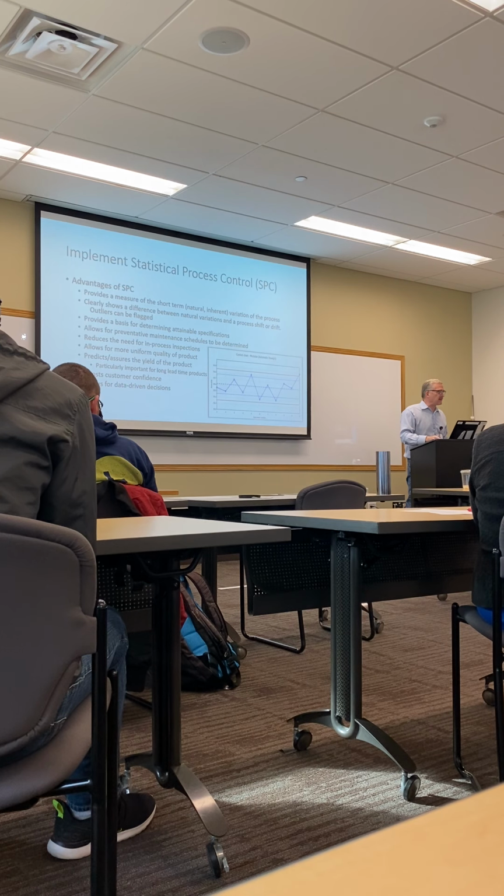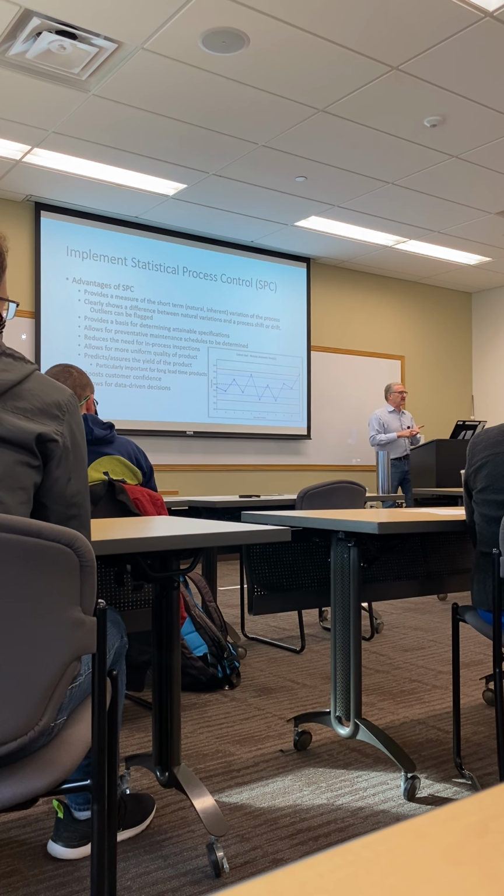That's all we know is at that step. At the next step, if we etch a hole in that oxide and the hole goes all the way down to the silicon, if we can measure that there's no oxide left in there or how thick the oxide is in there, then we can know at that step, only for that step, that it's going to be okay. But you see, if you measure every step, every tool, and every process on the tool, you can pretty much assure that it's going to be okay, that thing will yield, unless somebody pulls a moron move and hacks on it, or scratches something and physically breaks it.